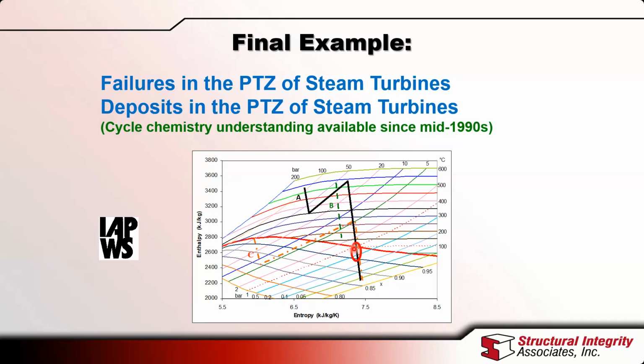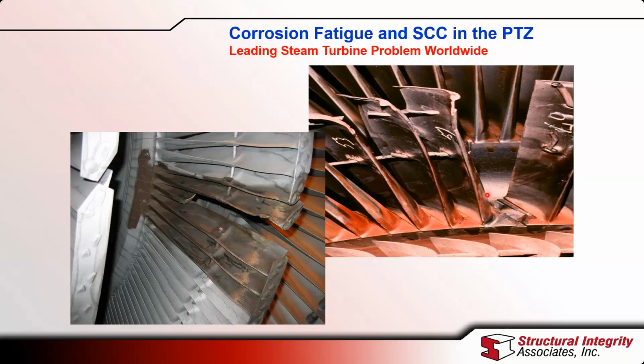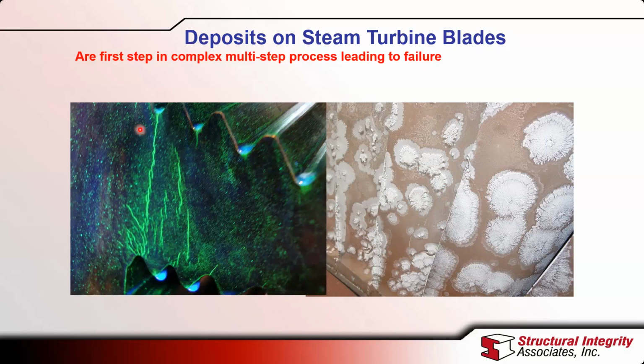And as that expansion line crosses the saturation line, this is the area that we talk about in terms of the phase transition. This is where the superheated steam starts to change to condensate. And this is the area where all of these failures take place, right here, because of this phase change. These are some of the damage that we see in the blades. We sometimes see in the attachment areas, when we do the NDE, cracks that go across the engaged threads, and sometimes see deposits on the blades themselves.